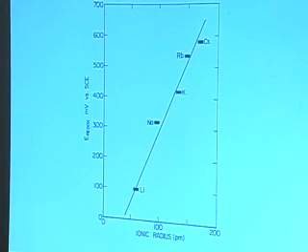So we were all excited about this. We thought about all kinds of things that we could do with this. But the first thing we could do is just say, hey, we have this neat system where the cation changes the redox potential over half a volt. Because one of the issues when you do all this Marcus theory stuff is that you might want to change, for example, this delta G term. But typically to do that, you have to change the nature of the molecule.